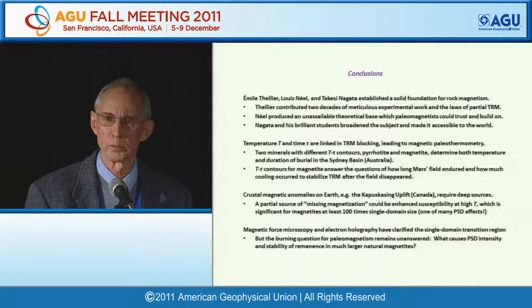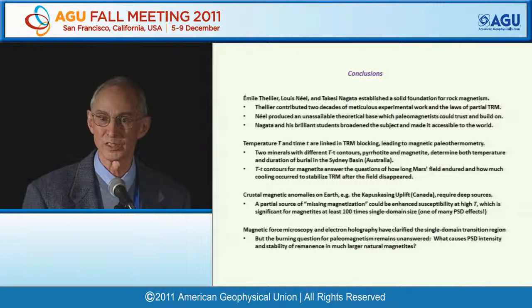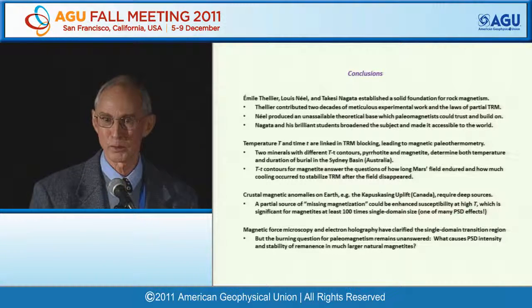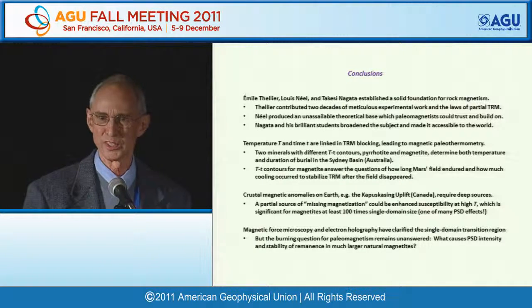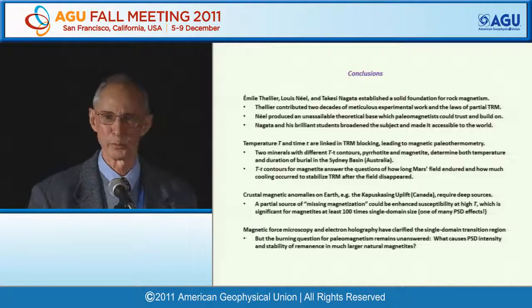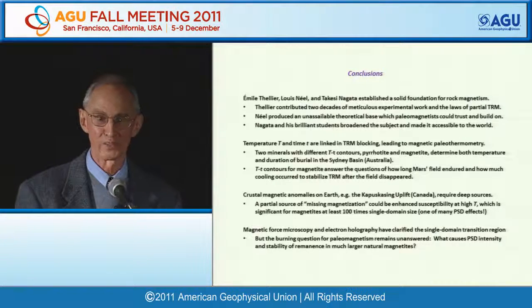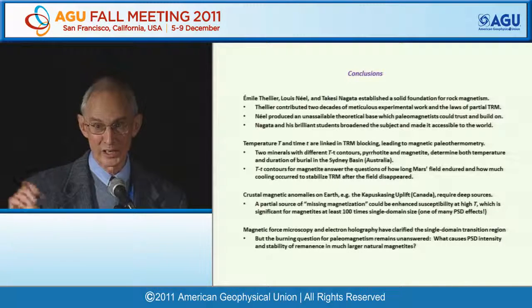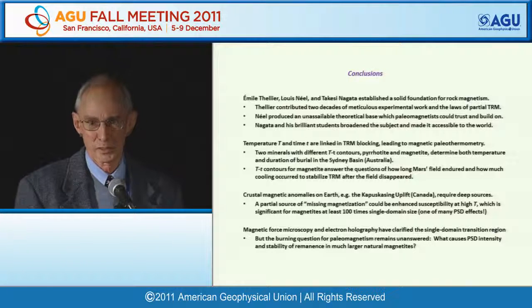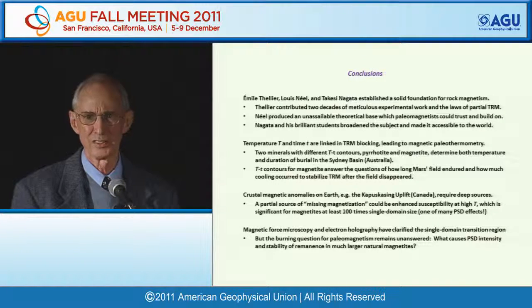In a quite old paper by Argyle and Dunlop, we showed that you can literally match these properties of the low temperature residual. Well, it's measured at room temperature, but it's what's left over after low temperature cycling. They really are indistinguishable from single domain properties. And that applies to grains which are really quite large. Certainly a micron and above, a few microns.